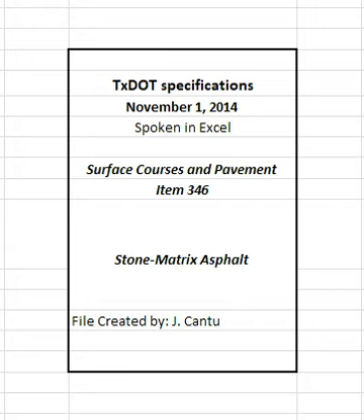Collect haul tickets from each load of mixture delivered to the project and provide the department's copy to the engineer approximately every hour or as directed. Use a handheld thermal camera or infrared thermometer, when a thermal imaging system is not used, to measure and record the internal temperature of the mixture as discharged from the truck or material transfer device, MTD, before or as the mix enters the paver and an approximate station number or GPS coordinates on each ticket.